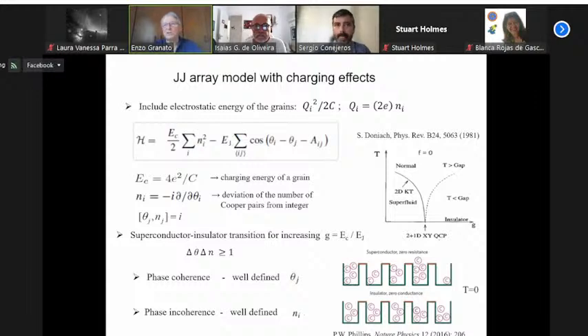So in the experimental system, which is not like an array, like a homogeneous film, what happens is that after you decrease the thickness, the system, even though it's homogeneous, is still made of superconducting regions. It doesn't have to be grains necessarily. It could be just local superconducting regions. And these local superconducting regions are very tiny. They are small. And since you are decreasing the amount of the part that's superconducting, you decrease the connections. Then the charging energy contributes more than the Josephson coupling. That's why you get the insulating effect.